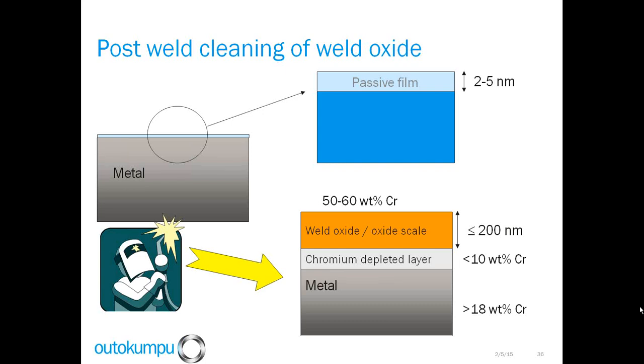When we do a welding operation, we create a high temperature oxide. That oxide on the surface is very high in chromium. Under that is a chromium depleted layer that has low corrosion resistance. Again, sometimes the chromium level is less than 10%. So we want to restore the corrosion resistance after welding. We need to remove the weld oxide as well as the chromium depleted layer. Again, we do that either through mechanical means or chemical means or a combination of the two.